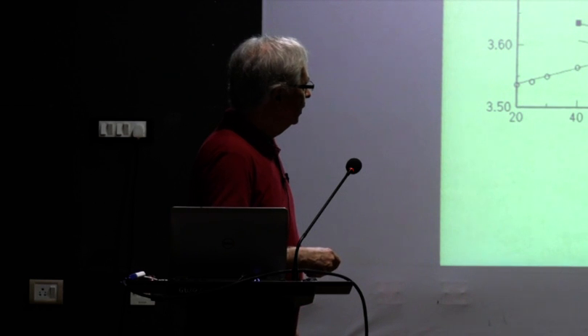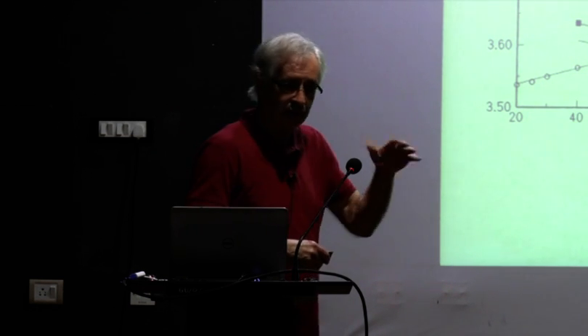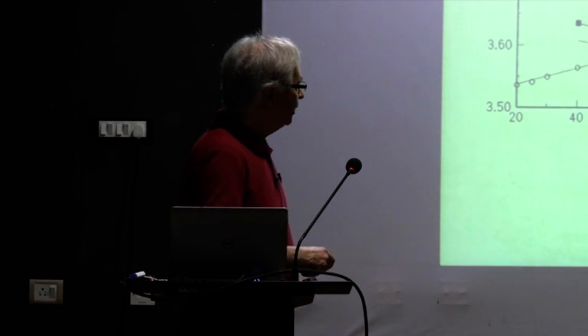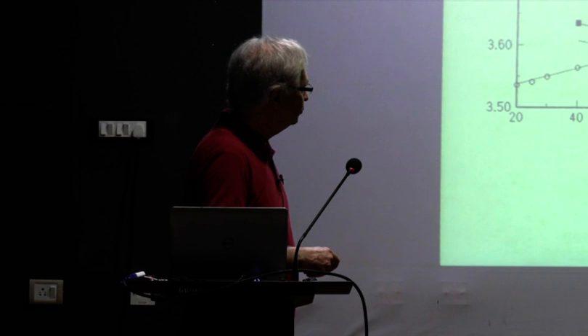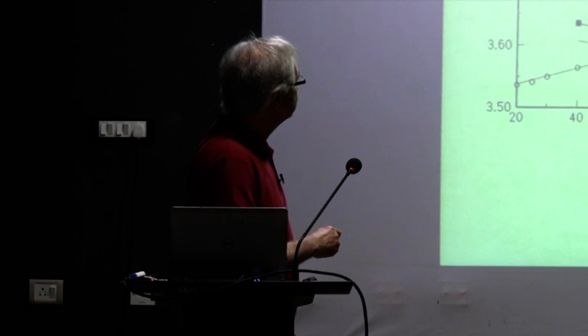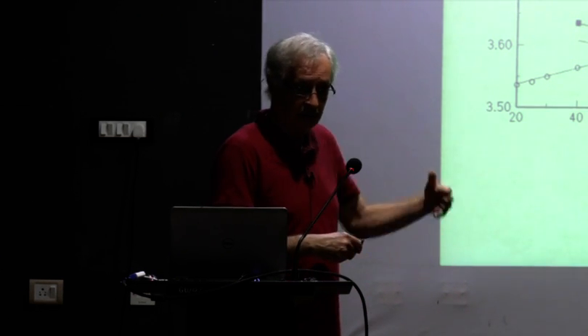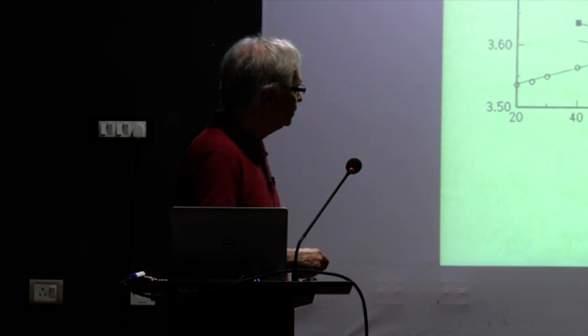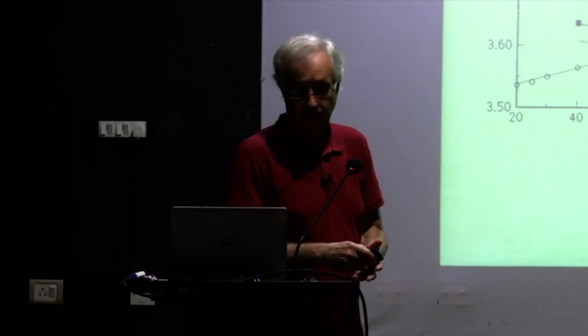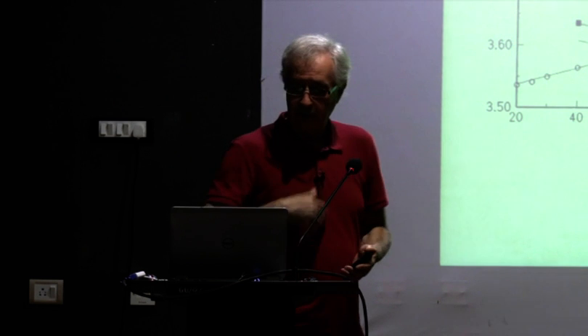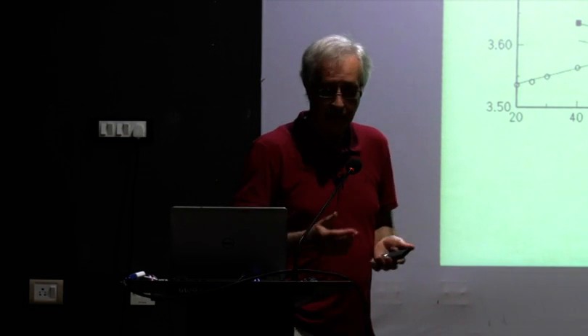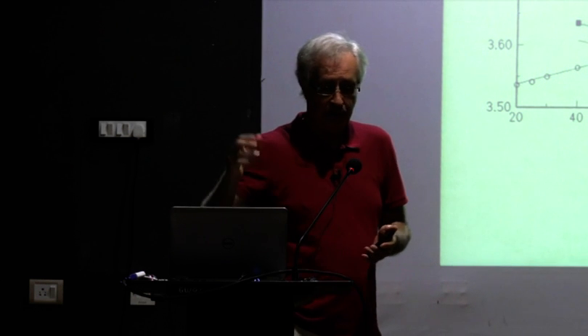What else do you have? You can measure the atomic volume in antiferromagnetic gamma iron by stabilizing it. And then it is also possible to check the room temperature value of FCC iron from such extrapolations that I showed you on the first curve. You can do this at low temperature or at room temperature. So you have these points over here. Somehow these points and these points have to join. And this, overall, gives you a very large thermal expansion coefficient.